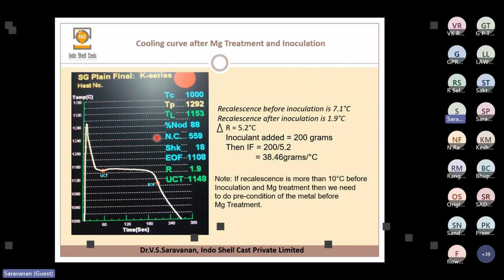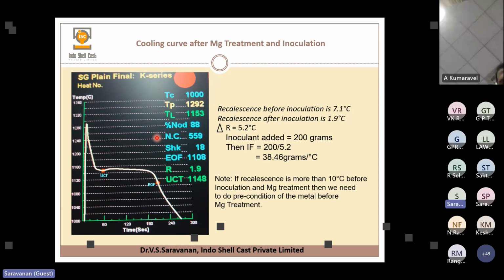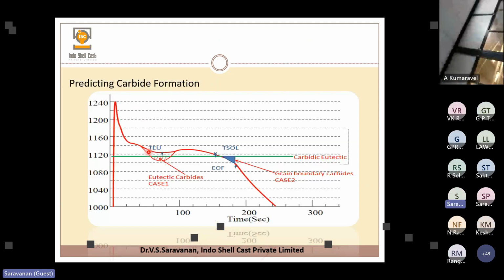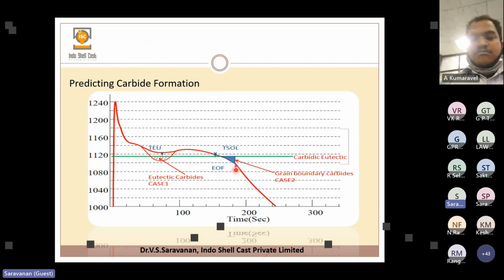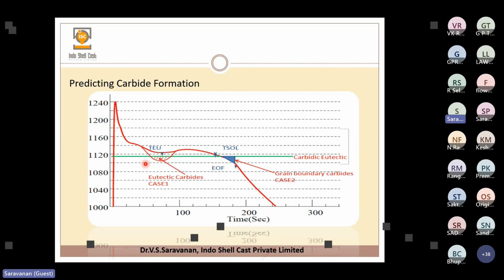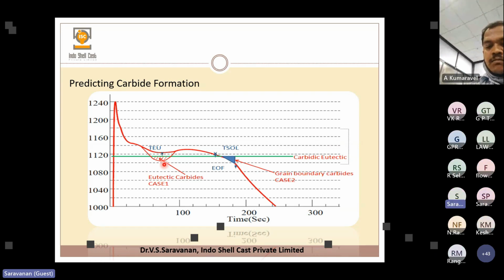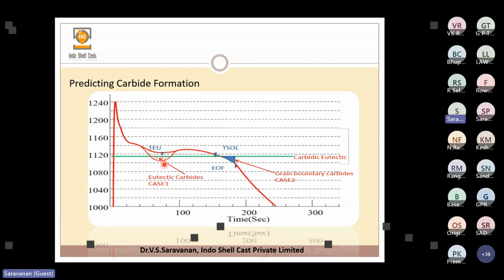These are some of the examples I'm just putting here. So you can see here, this is the carbide eutectic line. Sometimes if the TEU goes down like this instead of staying here, then we will get problems related to carbide. Sometimes it shows the nucleation is also not good, so it takes more time to create nucleation sites. Then again we get some porosity related issues also.